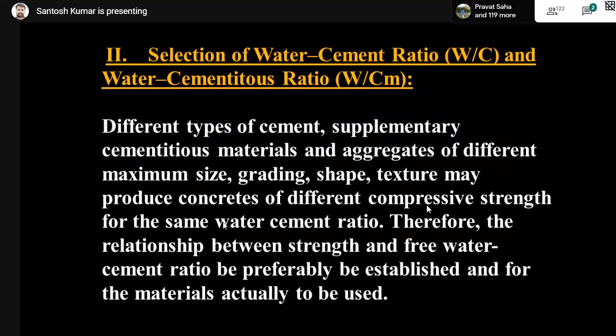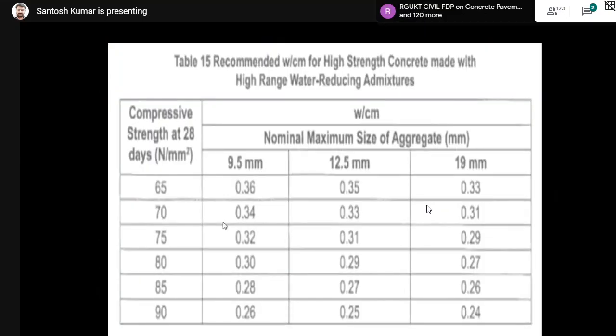Selection of water cement ratio mainly depends on the different types of cement you are using, supplementary cementitious materials, and aggregates of different sizes, shape and texture, and they produce different compressive strength results in your concrete. Therefore, the relationship between the strength and free water cement ratio shall preferably be established for the materials actually to be used. And this is Table 15 as per IRC 44, a recommended water cementitious ratio for high strength concrete made with high range water reducing admixtures. Now, today's example, I can take the example of compressive strength of 65 Newton per mm square. We are designing the concrete. So, if you are using 9.5 mm aggregate, the water cement ratio shall be taken as 0.36.